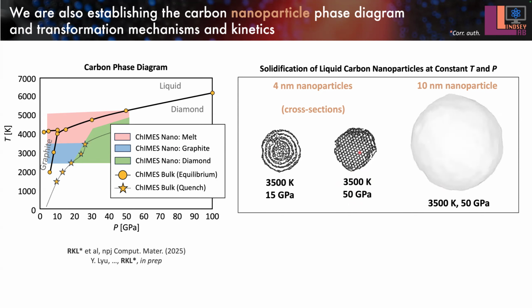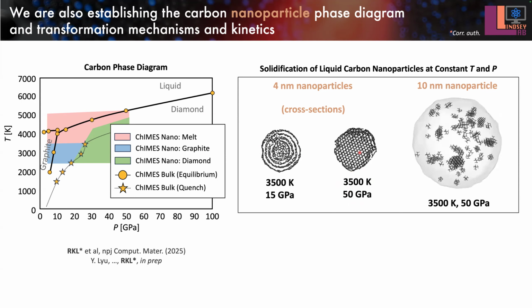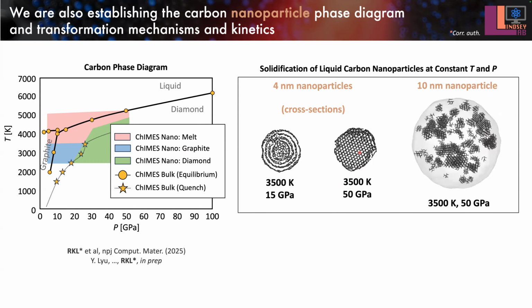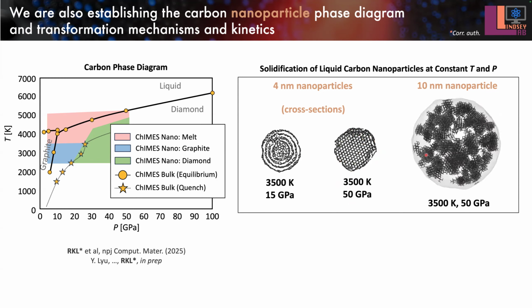In the case of this large particle, you see something that looks a lot more like classical nucleation, in that there's a bunch of seeds that form and vanish before you start to get seeds that begin to grow. And so the practical consequence of this, as you'll see in the simulation, is whereas we get a single nice nanodiamond here, you're going to see a lot of nanodiamond grains forming in this that will eventually grow and form boundaries between them.